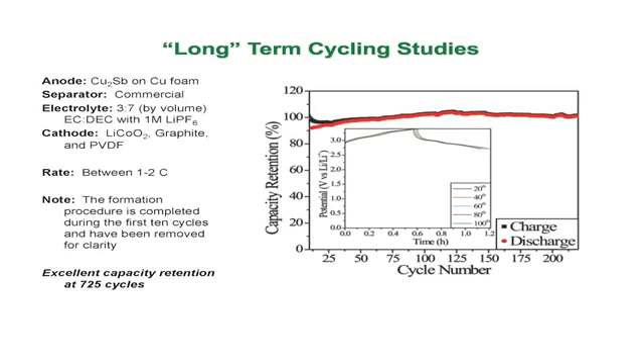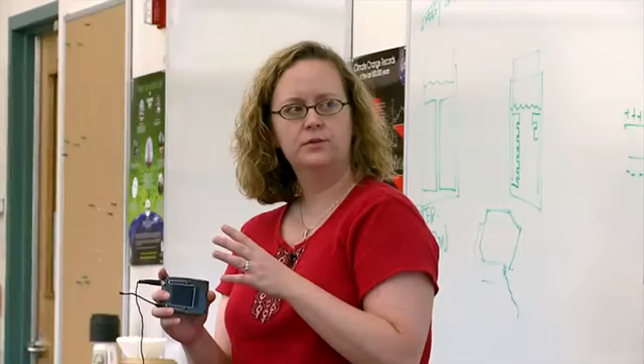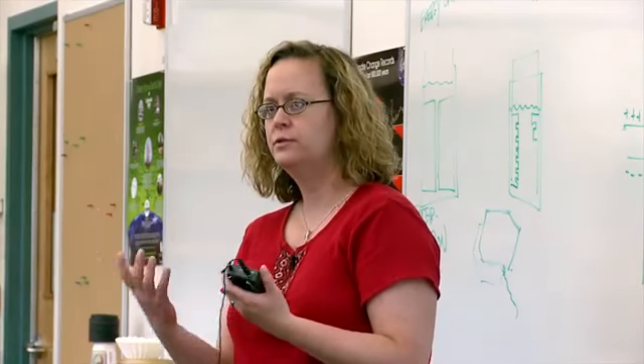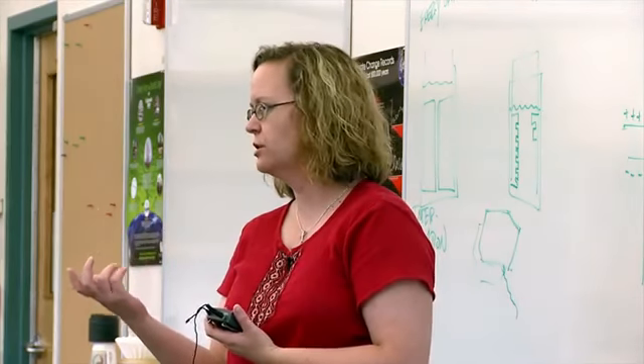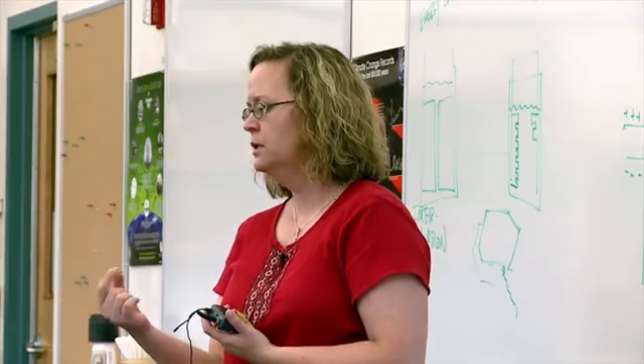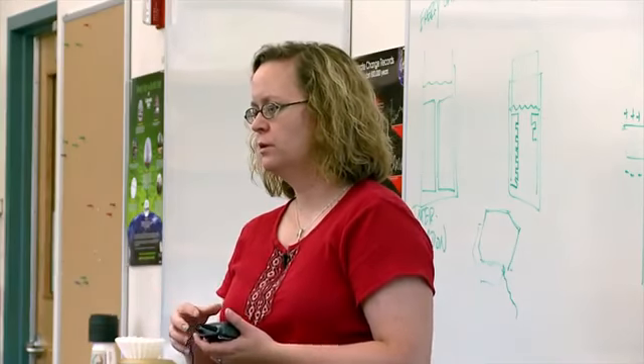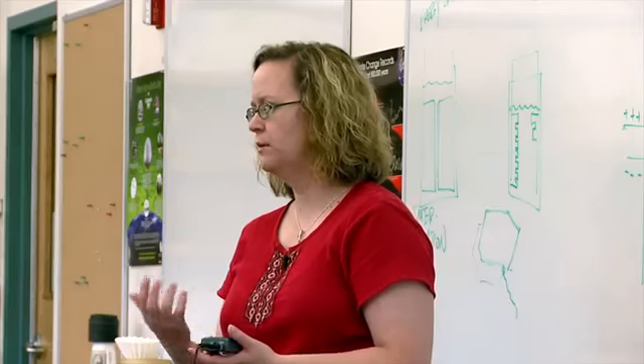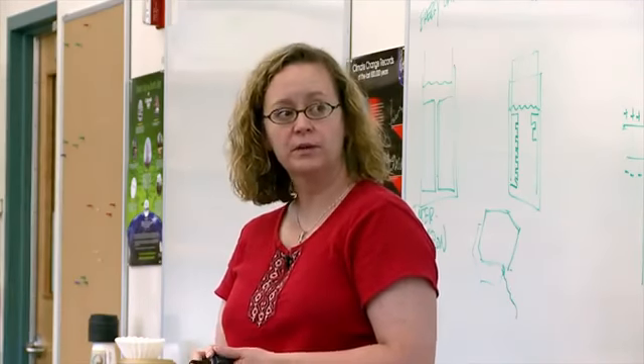This is the salt, LiPF6, that if it sees water, it makes HF acid, and that's what etches bones. So that's the bad part, but we used it for this test. Cathode is the commercially available cathode. We packaged it in the size and shape you would use for your phone, and we cycled it. Now, the key is that we cycled at a rate of 2C. So a C is fully charging and discharging your battery in 1 hour. Your cell phone's rated to work at about C divided by 3 or C divided by 5. And so we were going pretty fast.